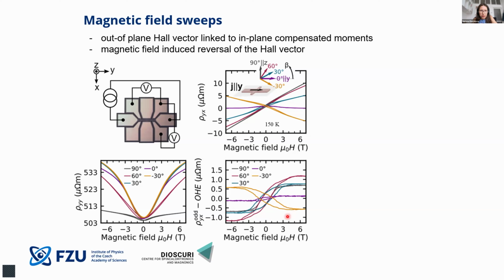And the third feature which I want to mention is that the largest signal appears when the magnetic field is not perfectly perpendicular, when the magnetic field is along this 60 degrees. And again, this is completely consistent with the observation that manganese telluride has these multiple domains, and they can be polarized by the in-plane component of the field, so one can maximize the signal. Nevertheless, one can also see that by applying 30 and minus 30 degrees, the signal reverses sign,